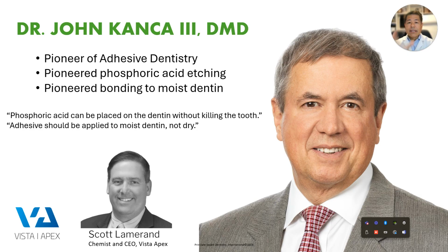So now we would have an adhesive with the BioGlass 45S5, and we would have restorative materials with the BioGlass 45S5, all in one. Now remember, what was happening at the time was we did have some bioactive materials, but at first some of these bioactive materials said, hey, just place it on the tooth. It'll bond to the tooth, and you'll have all this bioactivity. It's going to be the greatest thing. Well, what we found out was the bond strengths were really inadequate. So you would use this bioactive material, you would do your direct restoration, and over time that restoration would fail because it wasn't truly bonded to the tooth.